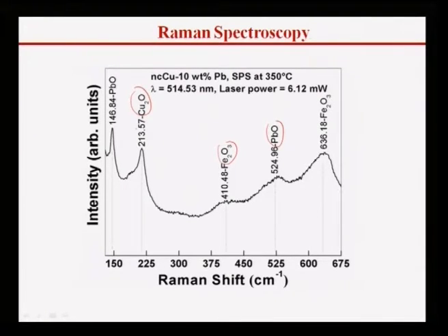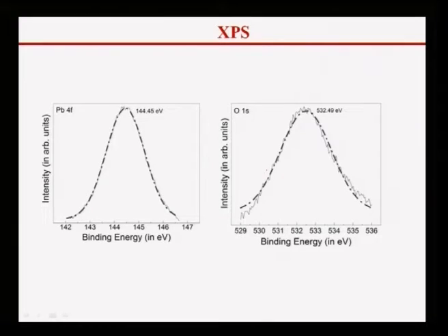Although Raman spectroscopy gives you very nice, very broad signals of the oxides, that may not be sufficient to really pinpoint what kind of lead oxide is present. That is, the electronic state of the lead and oxygen is not clear. That can only be done if we use XPS, X-ray photoelectron spectroscopy, and that is done here. As you can see very clearly, this is the state of the lead of such particles on the worn surface, and this is the energy level, the binding energy.